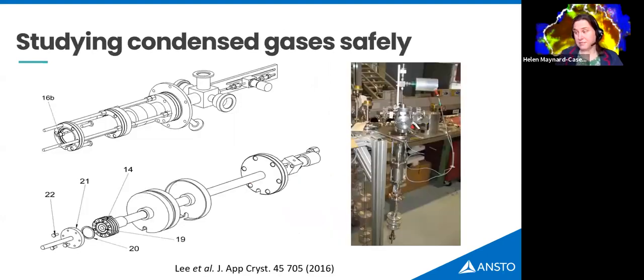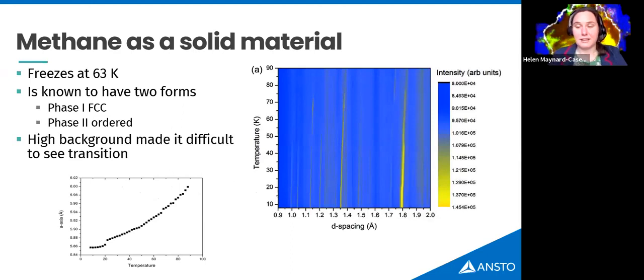But I noticed that no one knew the thermal expansion of nitrogen and methane over the Pluto seasonal variation, and I should say that that's a relatively straightforward experiment for me to do. One of the reasons is that we've adapted these gas delivery sticks, which go into our cryostat. They were originally designed to do gas dosing experiments for metal organic frameworks, so I've appropriated them to do some planetary science. And so it means that I can condense things like methane and nitrogen all the way down to around 5 Kelvin or so without too much trouble.